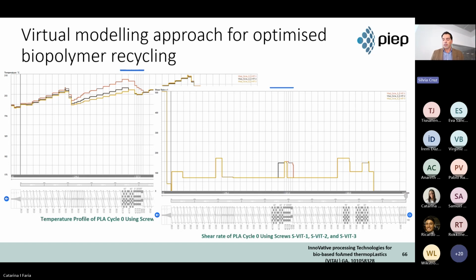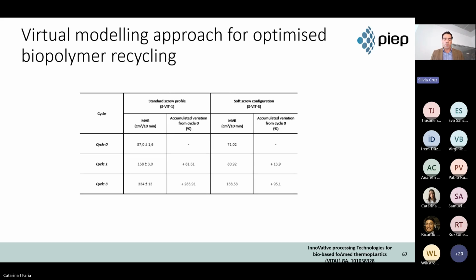With this, we then ran again some real experiments on the compounding with these elements and with these screws, and actually we get a real change in the degradation of the material. So in the table we compare the most aggressive and the less aggressive configurations between cycles 0, 1, and 5, and what we get is a major difference in the MVR results. So actually, this change in the screw configuration, I would say, is more relevant, at least from the results that we get during the project.